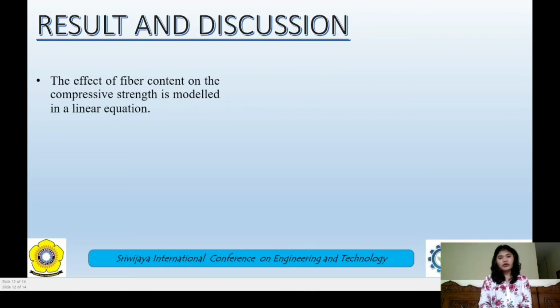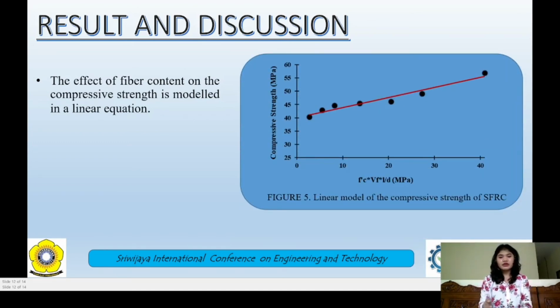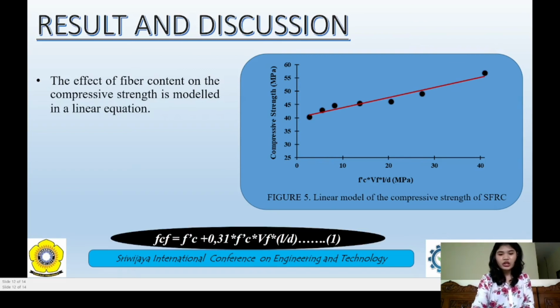The effect of fiber content on the compressive strength is modeled in a linear equation. We can see figure 5 about the linear model of the compressive strength of SFRC, and the equation is presented in equation 1. From equation 1, we can see f_cf is the compressive strength of SFRC, Vf is the fiber content, and L/D is the aspect ratio.